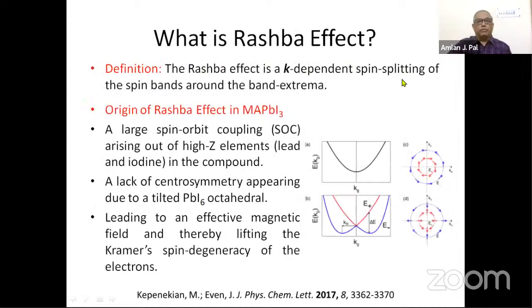So what is the Rashba effect? The Rashba effect says that it's a kind of k-dependent spin splitting of the conduction band and valence band, any of the band extrema. That is, the conduction band or the valence band, they are split. They are spin split basically. Let me just tell the origin, why this Rashba effect will occur at all in methylammonium lead iodide.